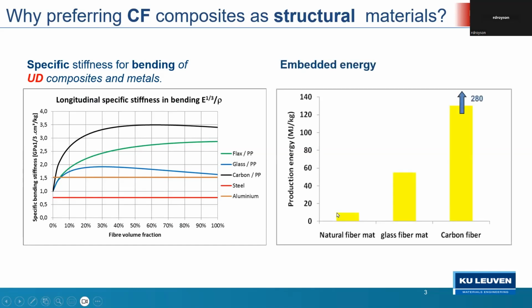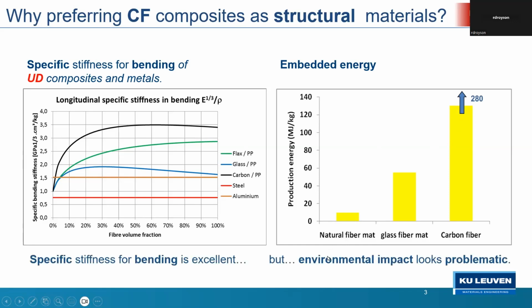But there is a but. As far as we understand, the embedded energy, as a metric for the ecological impact of carbon fibers when you produce the carbon fiber, not when you use it, because then you make the structures lighter and you save energy, but just the embedded energy in the carbon fiber itself seems to be much, much higher than glass fibers and evidently much higher than natural fibers. But the question is, how reliable are these data?